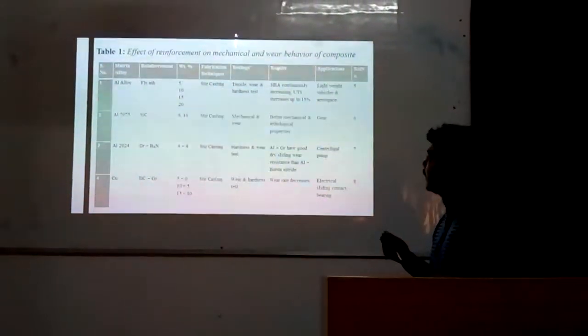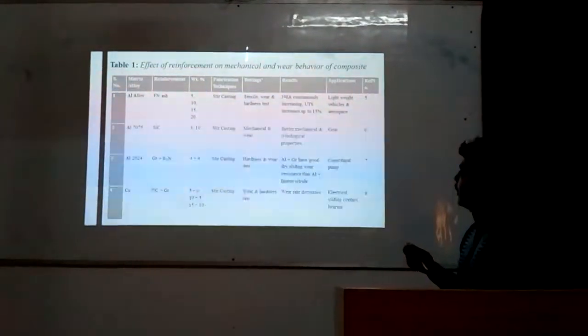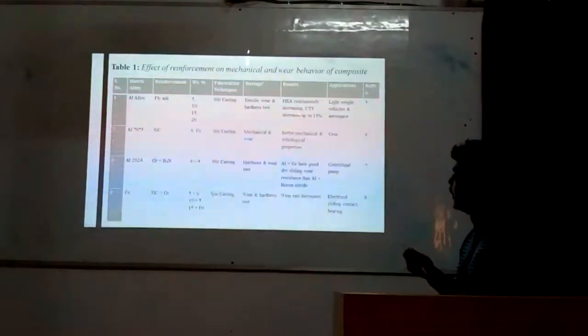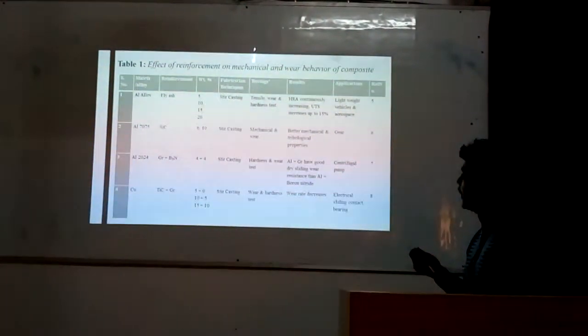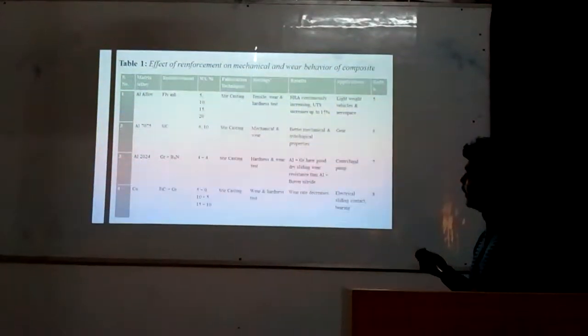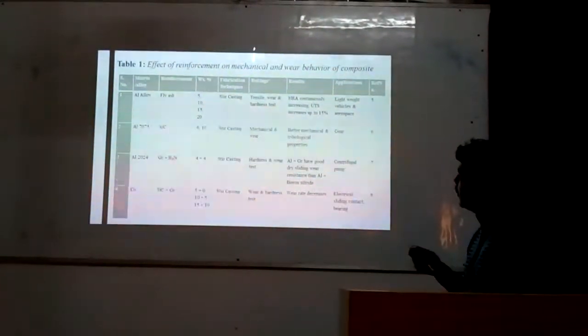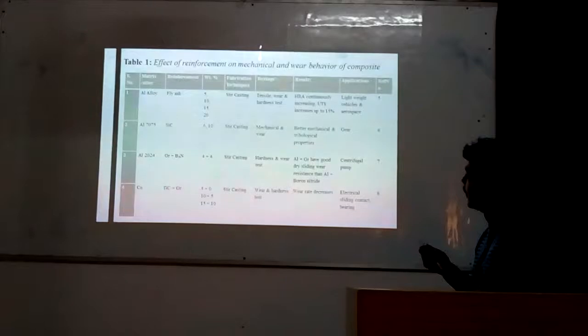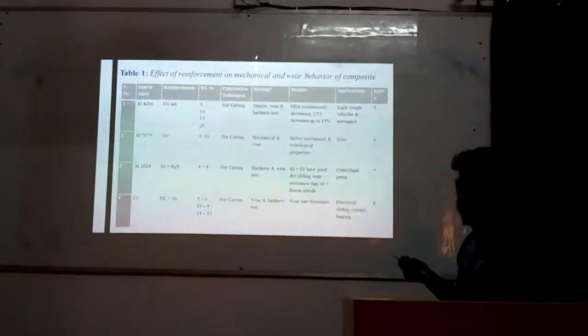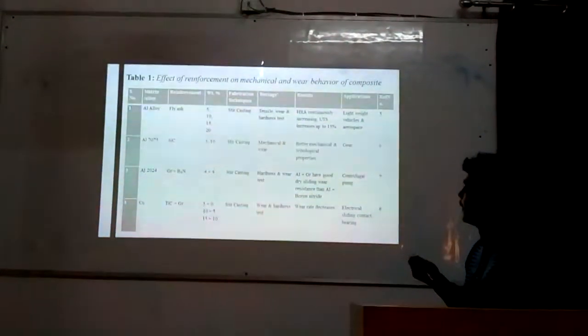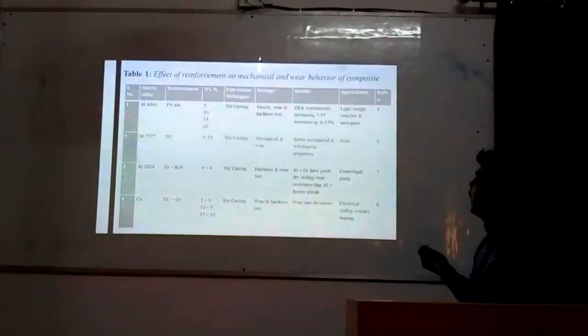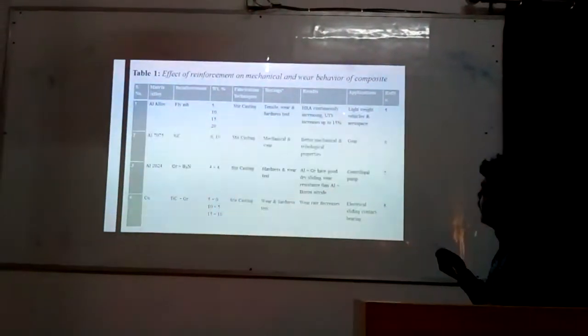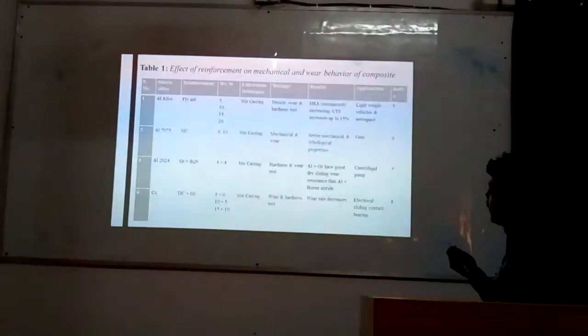The results obtained show hardness continuously increasing, ultimate tensile strength increases up to 15%, and after that the ultimate tensile strength starts decreasing up to 20%. Applications where you can utilize this are light vehicles and aerospace.